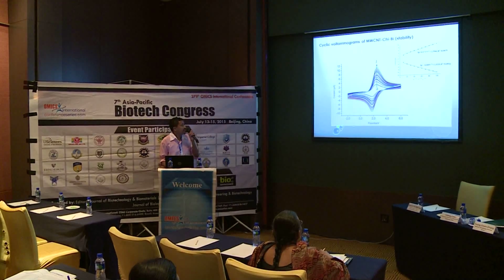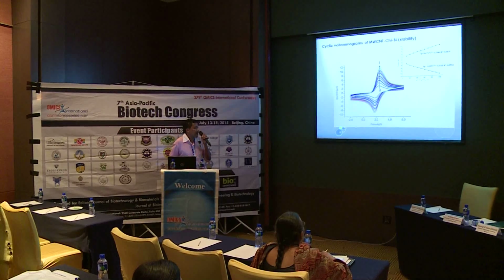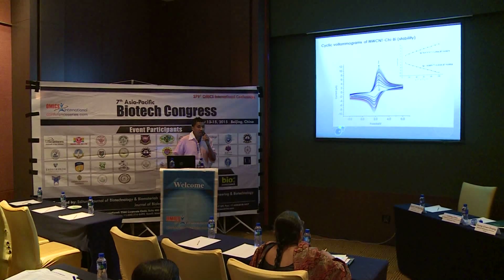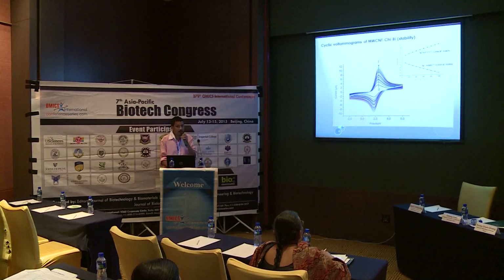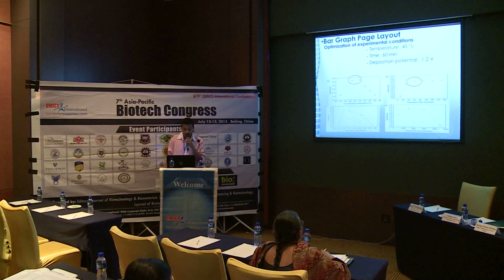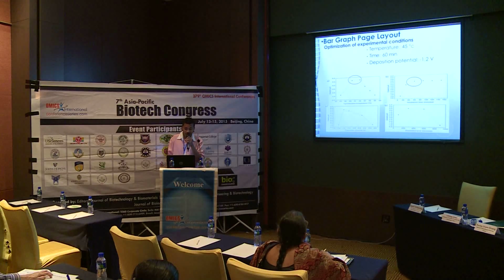So this is the linearity of our experiment. It shows high stability when we cover our electrode with multiwalled carbon nanotube. So this is some optimization. This is temperature. We found it's 45 degrees, time is 60 minutes. And also the deposition potential, minus 1.2 volts. It's very, very important, because if it's less, it can have problems for deposition. If it's more, it can destroy your nanoparticle. You cannot detect anything.